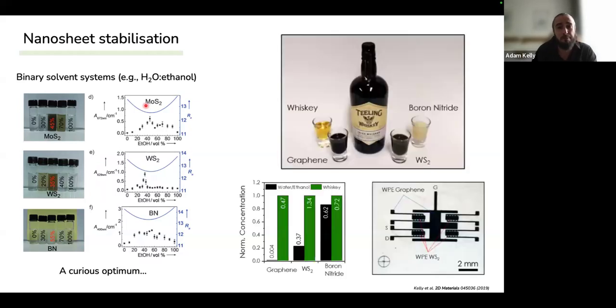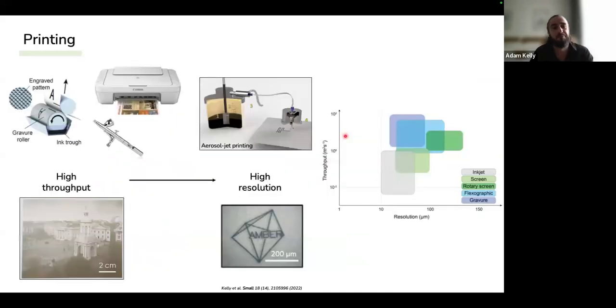And we decided to wonder, will this actually work with commercial whiskey, for example? So we went down to the supermarket, we bought some whiskey, and we tried to apply this process. And what we found was, yes, of course, the 40% ethanol to water worked, and the whiskey compounds themselves that leach in from the barrel during the maturation process, this actually provided even more benefits of stabilization itself. So this allowed us to create what we called whiskey phase exfoliation. So the point of this was just to demonstrate the versatility of this technique.